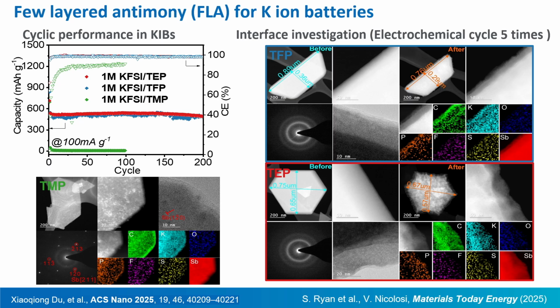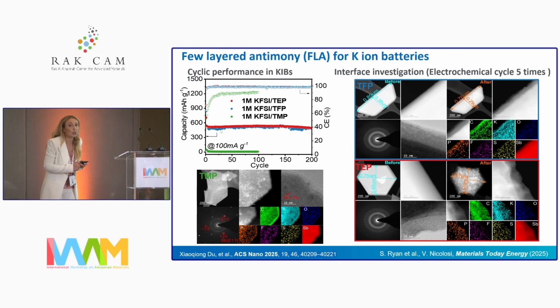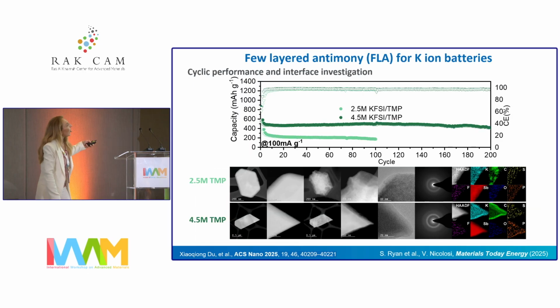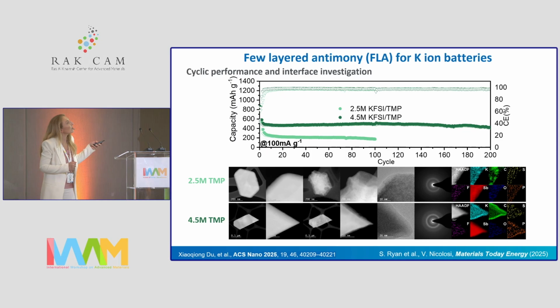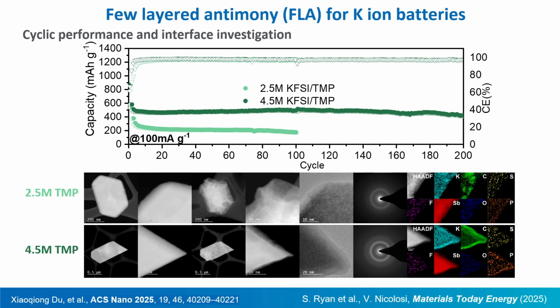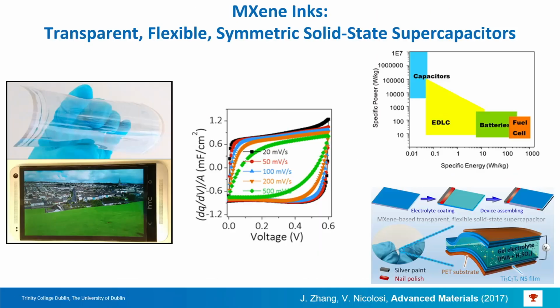Same thing in the TEP, although there is some degradation after cycling. The TMP was the one where we had more issues, especially with oxidation. In this case, we realized that the biggest problem there was the low concentration. Once we went to a higher concentration of electrolyte salt, then we managed to improve the performance also.